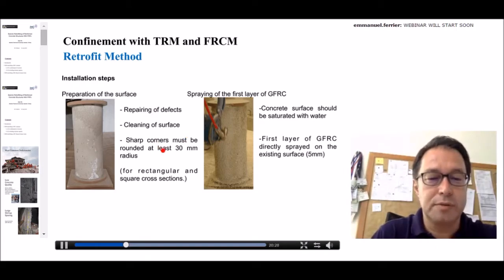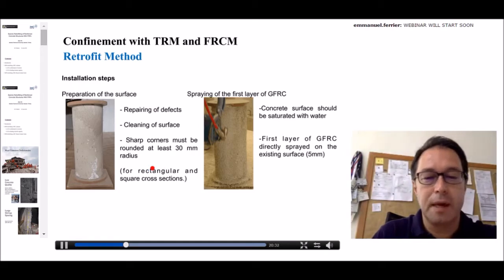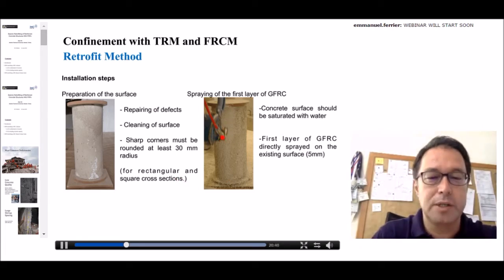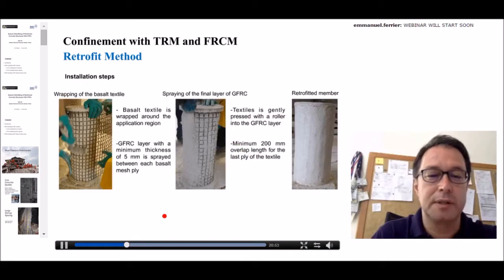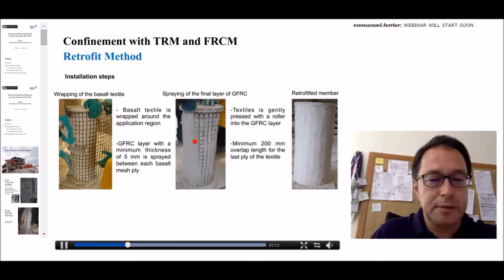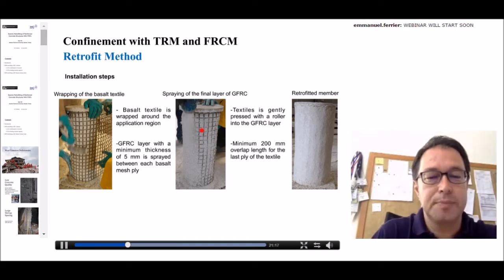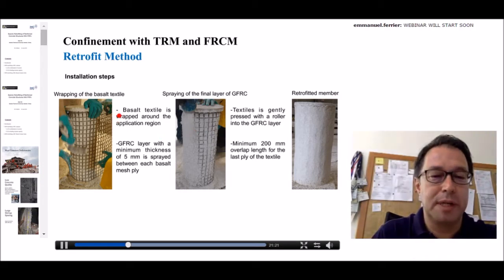Firstly, we repaired the defects on the surface of the columns. We cleaned the surface. We rounded the corners to a radius of 30 millimeter. That's valid for rectangular sections. And then we sprayed, I should say that this is a kind of sprayed concrete. We sprayed the glass fiber cementitious composite. And then we applied the first layer, and maybe in the next slide, it's better. And we applied basalt textile in this case, but we also use carbon textile and other types of materials. Then we applied the next layer of sprayed GFRC, which is glass fiber reinforced concrete. So each layer is about half centimeter, 5 millimeters, which includes a layer of GFRC and a layer of basalt textile mesh. At the end, you have such kind of appearance.